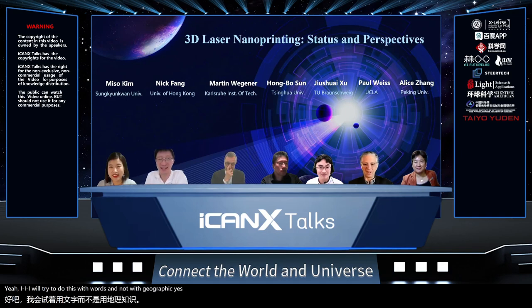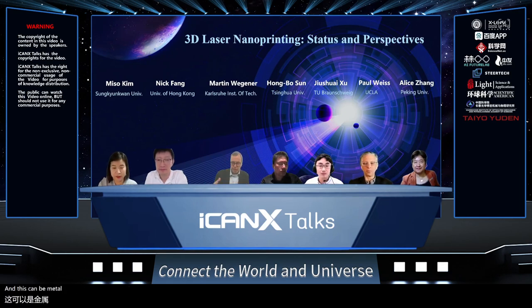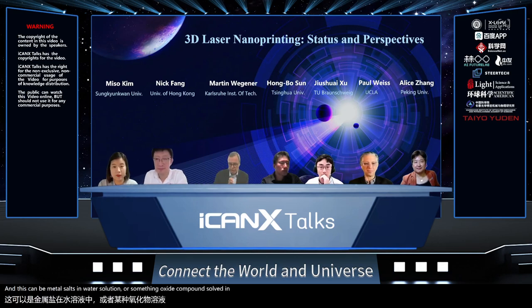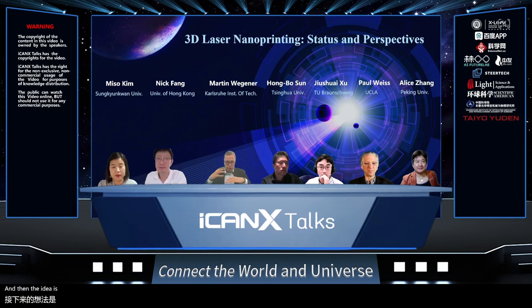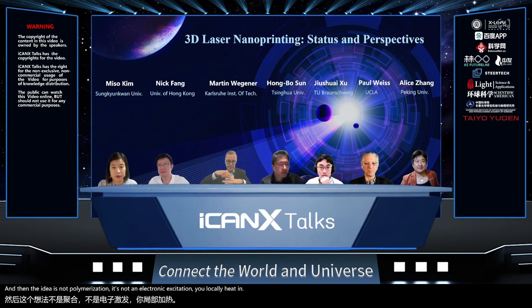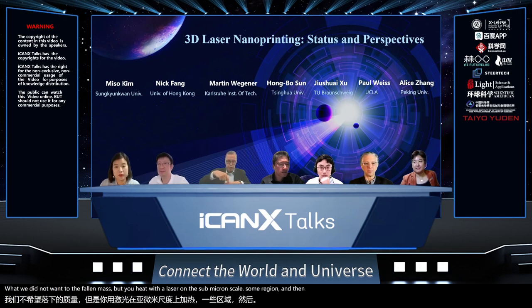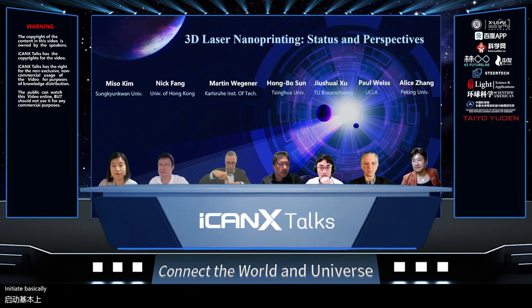Yes, thank you. Basically, what we do is we take completely different inks. This can be metal salts in water solution or some zinc oxide compound dissolved in water. And then the idea is not polymerization. It's not an electronic excitation. You locally heat with a laser on a submicron scale some region, and then you initiate basically crystal growth at this location. It's quite funny. And this seems to be fairly general.